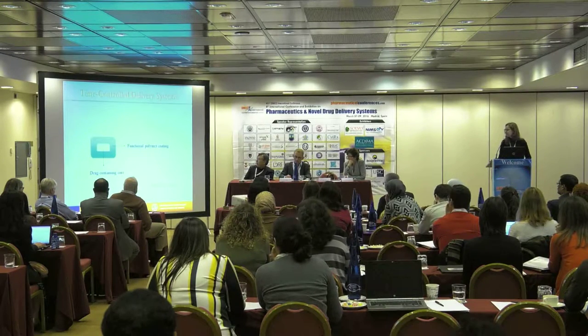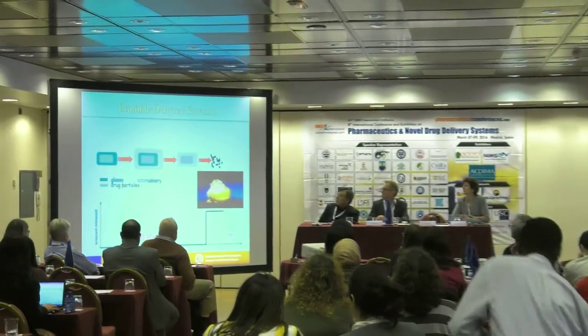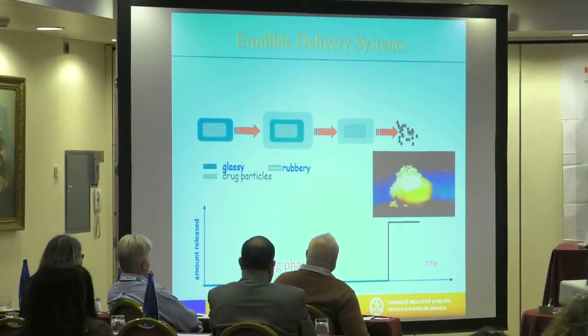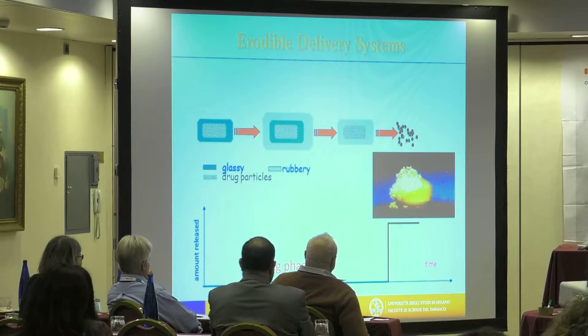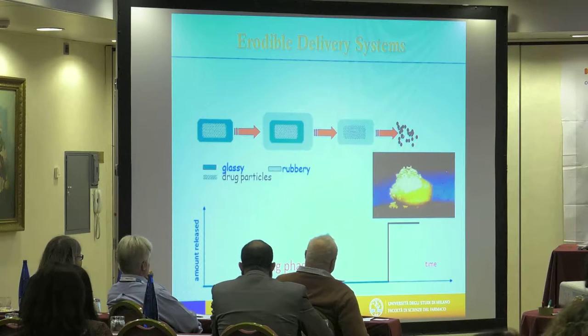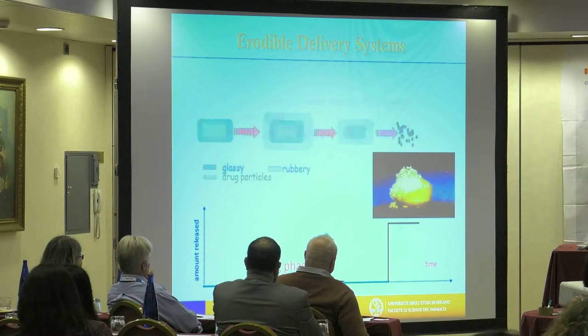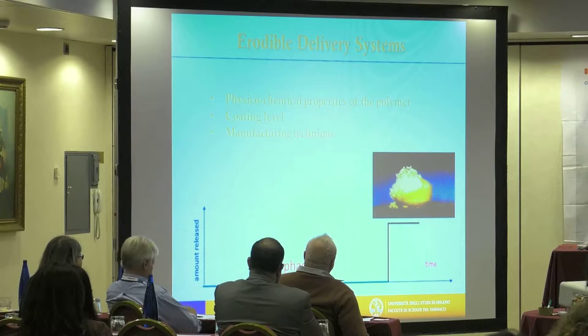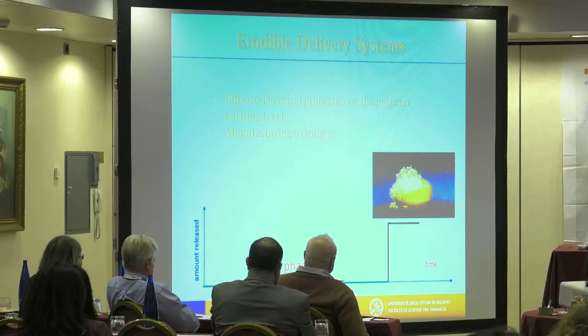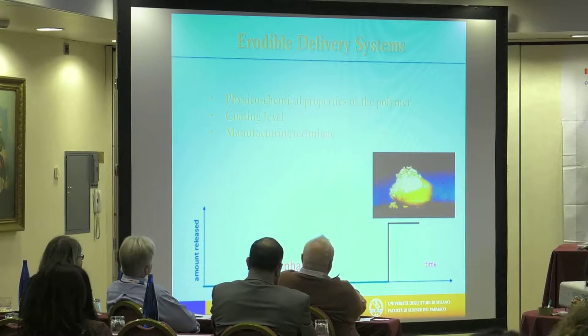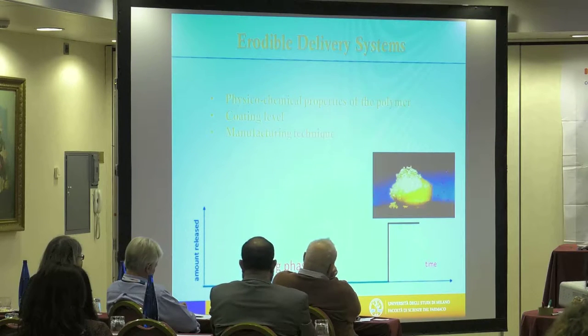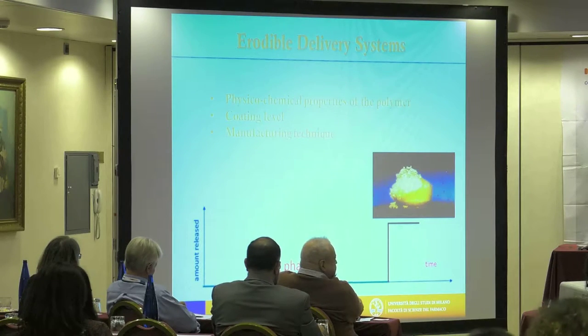Erodible coatings are generally composed of swellable hydrophilic polymers that, when exposed to aqueous medium, go through a glassy-rubbery transition, and as a result of the transition, a gel layer is formed and the rubbery polymer undergoes progressive dissolution and erosion until the drug-containing core is no longer shielded from the outer medium and drug release can finally take place. The duration of the lag phase imparted depends on the physicochemical properties of the polymer, primarily its molecular weight and its viscosity, and on the coating level. The manufacturing technique may also affect the structure of the coating and thus, to some extent, its functionality.